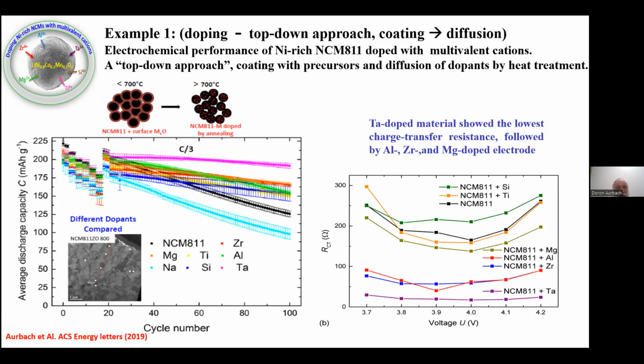So this doping changes the structure. We can do the doping in two ways, top down and bottom up. Here I show an experiment where we look very fast at the effect of different dopants, and the preparation is relatively simple. We take materials, even commercial materials, and we put them in a solution containing the alkoxide of the metals. We dry, so now we have a coating with the alkoxide, and then heat treatment at high temperature destroys the alkoxide, the anion, and now the cations simply go inside, and we have a diffusion of the cation inside.